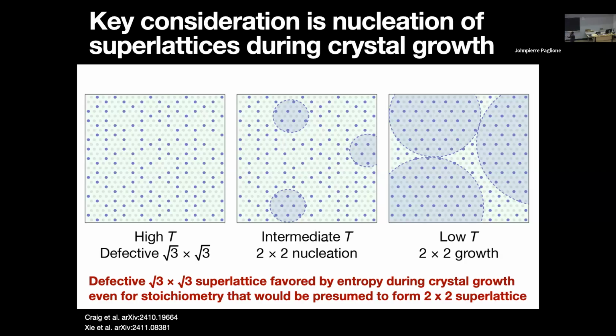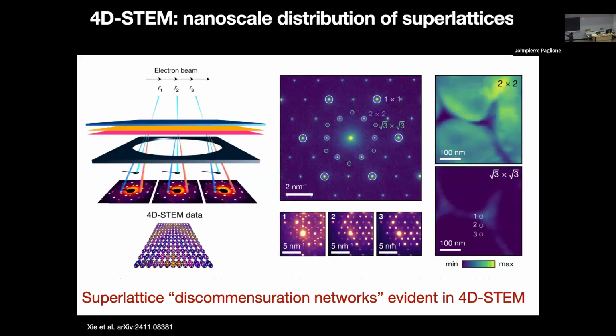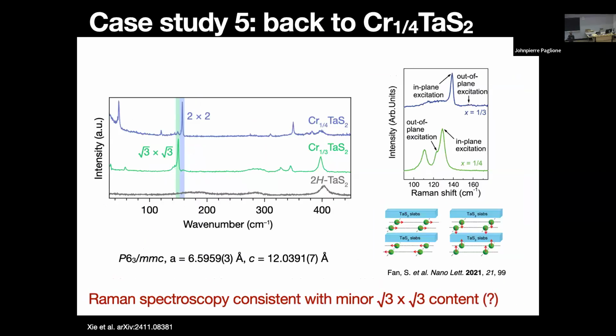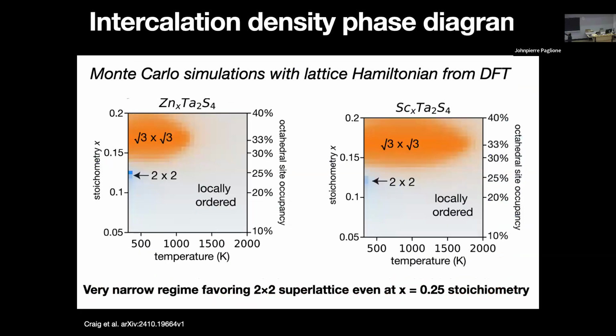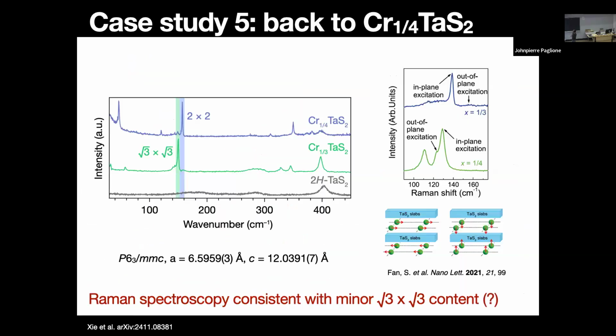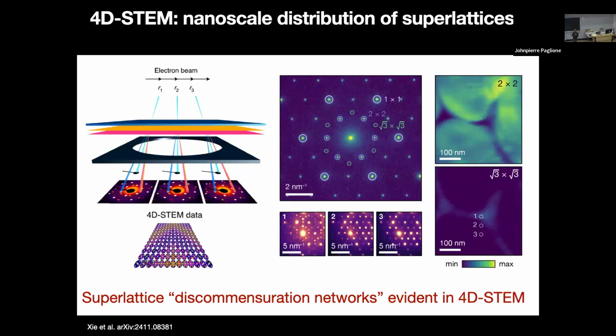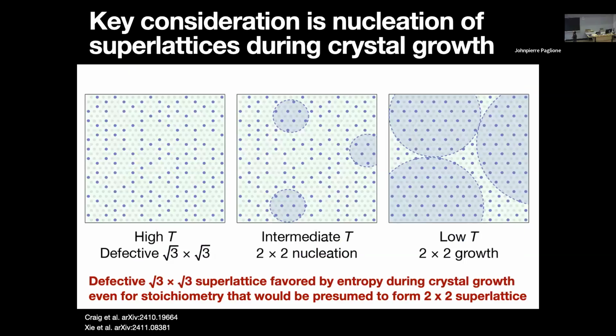For example, in some preliminary work, we've shown that if we grow these compositions at the 1/4 and deliberately quench them, we get Raman features that are exclusively root 3x3 because we are trapping it. And then if you anneal it slowly, you can get the 2x2 structure. So that is an important consideration because it can lead to extrinsic effects in the measurements.